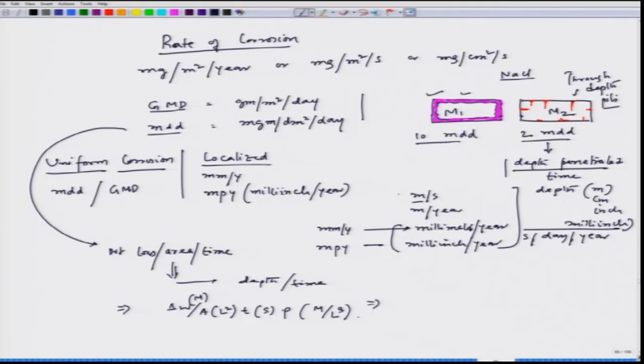So, now if we see that, it comes about L by second, or distance penetrated per unit time, or we can call it depth, isn't it? So, it is simply dividing the MDD by the density of that material. So, then we will convert the uniform mode of corrosion to localized mode of corrosion.